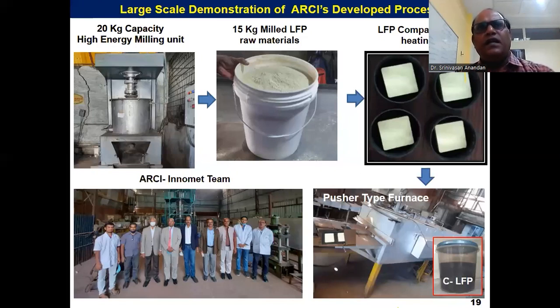With that facility, we could demonstrate our ARCI developed LFP process for making 20 kg LFP per batch. This is the large scale attrition milling unit where we can do 20 kg milling, and we have done 15 kg LFP raw material. So we have done the milling. Subsequently, we have done the compaction of that milled material, since we apply vacuum during the heating, and if you use the powder, it may fly. That is the reason we are compacting, and then the compact has been heated in the furnace to get the final LiFePO4, and this is our entire team, the industry as well as ARCI team involved in the production of LiFePO4.